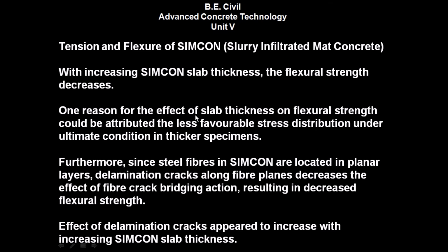One reason for the effect of slab thickness on flexural strength could be attributed to the less favorable stress distribution under ultimate condition in thicker specimens. Furthermore, since steel fibers in SIMCON are located in planar layers, delamination cracks along fiber planes decrease the effect of fiber crack bridging action, resulting in decreased flexural strength. Effect of delamination cracks appears to increase with increase in SIMCON slab thickness.